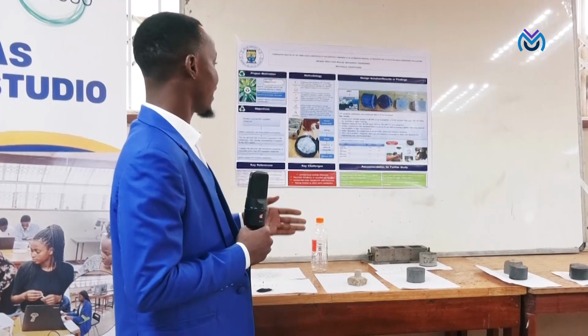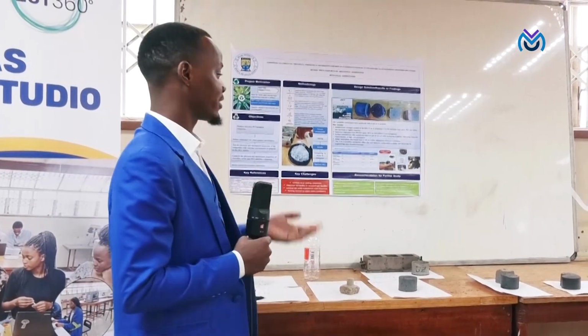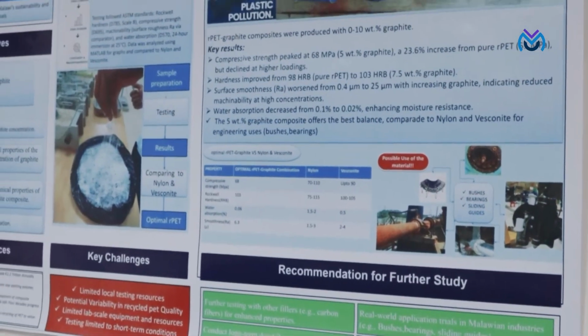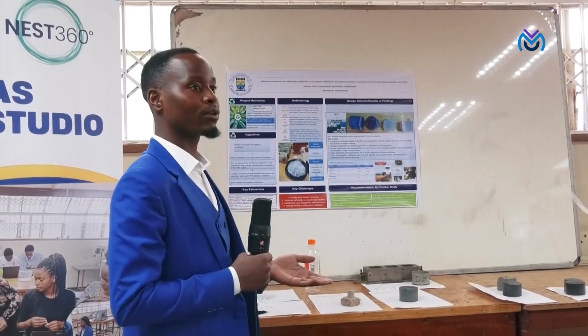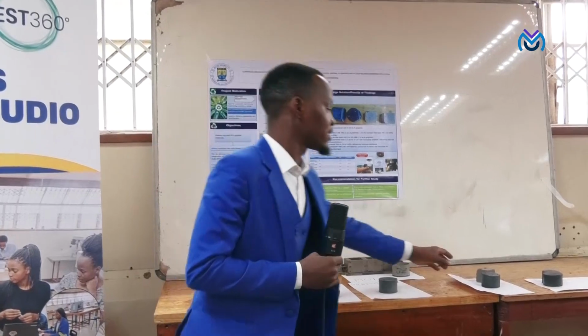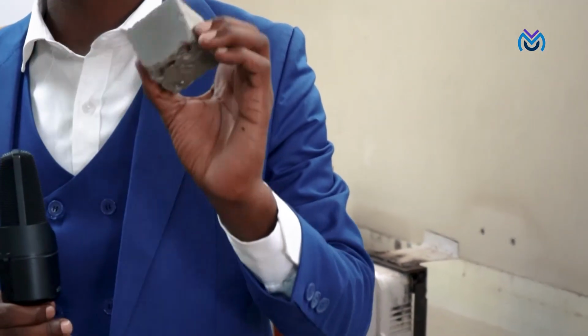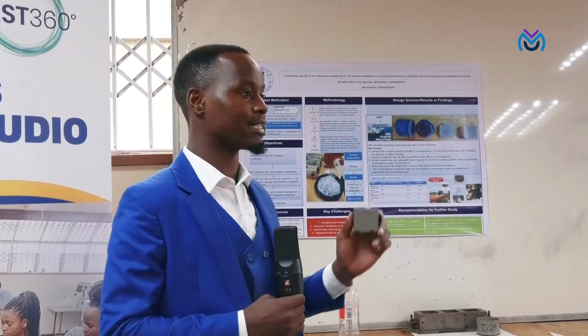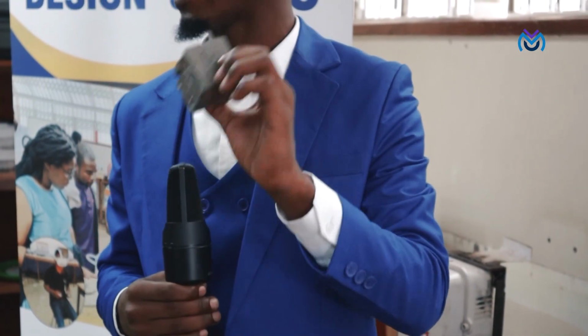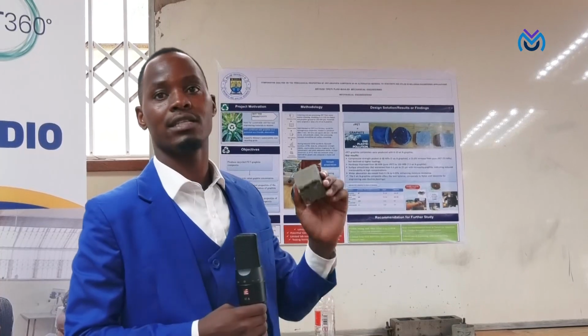a compressive test. We came up with graphs, and after analyzing the compression test, we found that sample number 3, which has 5% graphite, has properties which mimic nylon as well as Vesconite. This sample has 5% graphite, which means it has 95% recycled polyethylene terephthalate. Among those samples, this one has a high compressive strength of 68 megapascals. So this sample mimics the characteristics of nylon, because nylon has a compressive strength of 70 up to